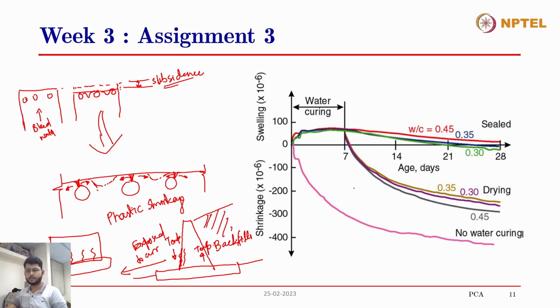And this is another image I have taken from the PCA document, the Portland Cement Association document, and this compares the shrinkage and the swelling in different types of concrete under different conditions. You can see that the concrete that is not cured in water will have higher shrinkage, while there will be no swelling. But when you're curing the concrete in water, that creates some kind of swelling inside the concrete, because the pores of this concrete are continuously filled with water, and because water gets sucked in from outside, that will create swelling inside the concrete, because the size of the voids will expand.